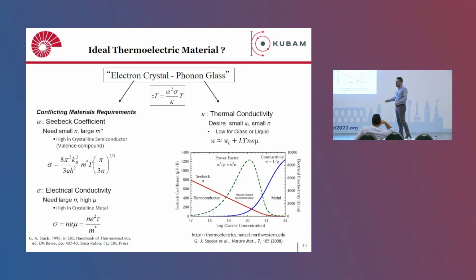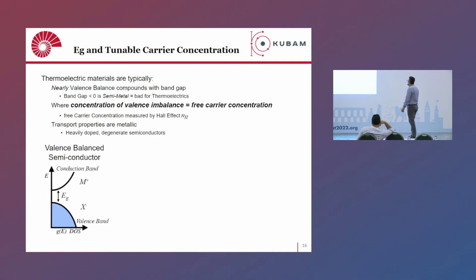So for the thermal conductivity part, you can see that this is composed of two contributions. One is the lattice thermal conductivity. Another one is the electronic thermal conductivity. So this is the Wiedemann-Franz law. So the electronic portion of thermal conductivity depends also on the electronic structure of the material. Now the only thing which is actually independent of the electronic structure is the lattice thermal conductivity. So it means we have to find some materials that display good electronic properties and low thermal conductivity. And you can tune these properties either by charge carrier optimization or lowering the lattice thermal conductivity. So let me describe how we can do that.